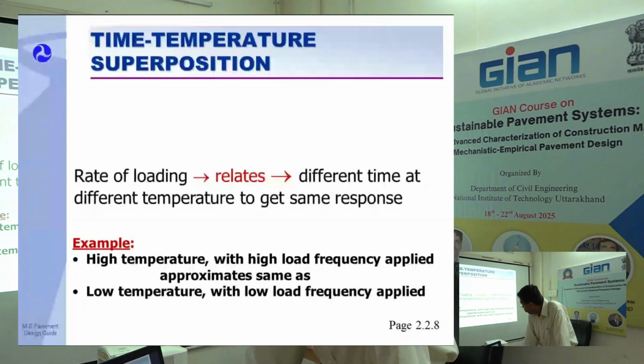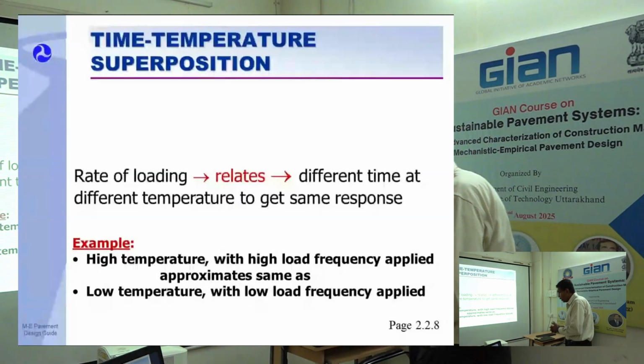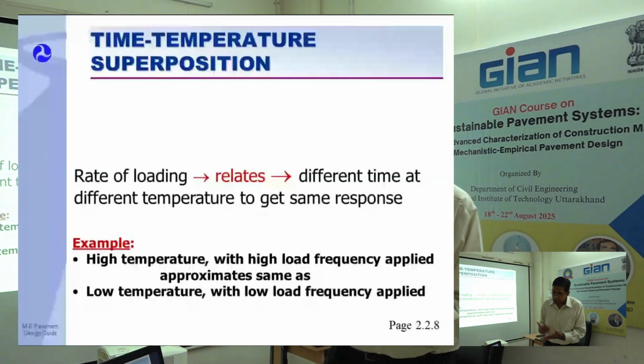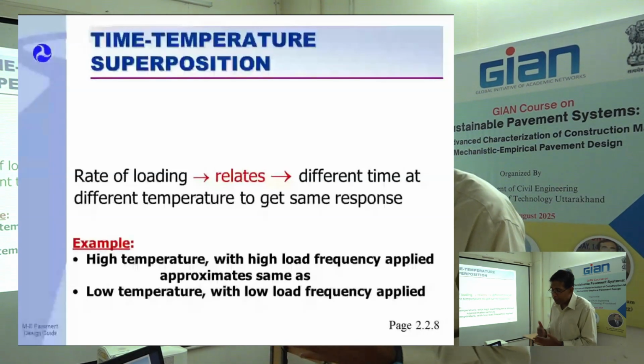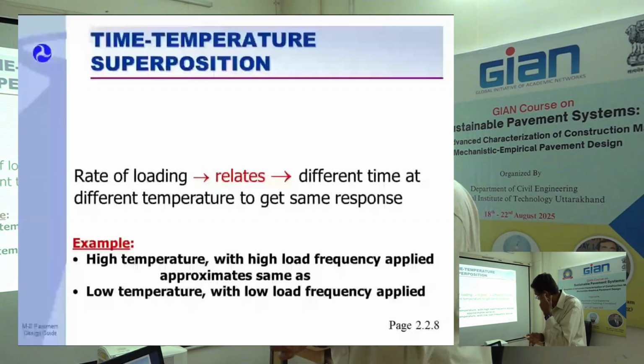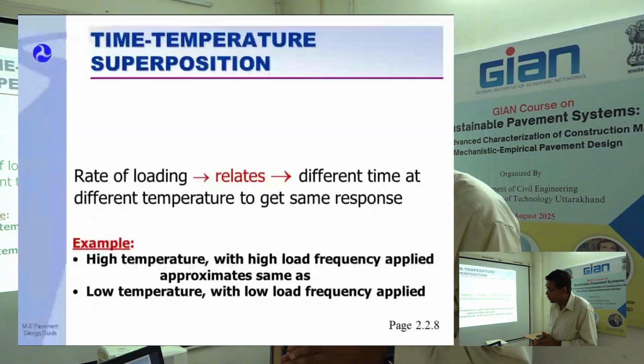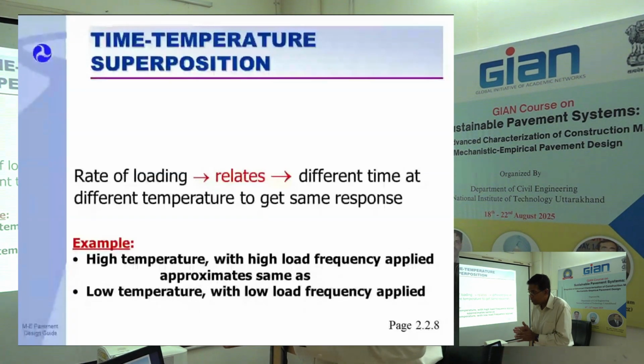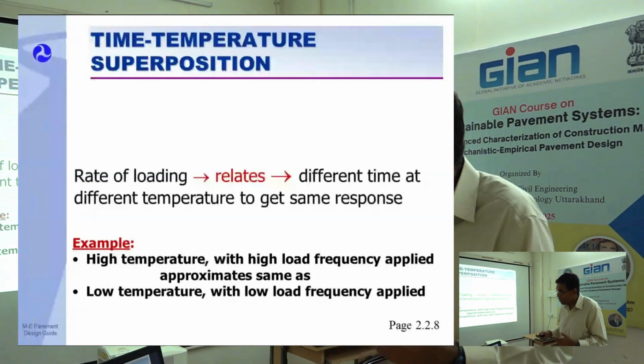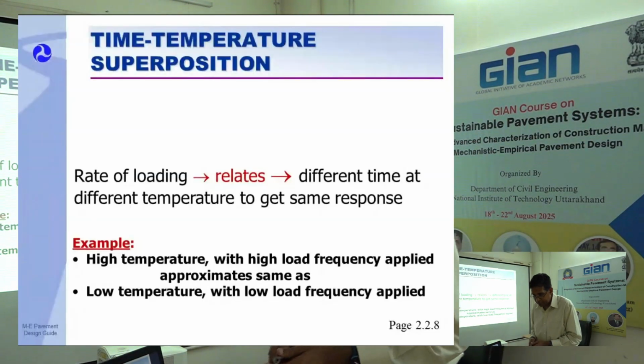Yeah, I think this is the resilient modulus. The dynamic modulus at a given temperature and frequency for asphalt is the resilient modulus. So it is the equivalent resilient modulus for asphalt concrete. So the resilient modulus in AASHTO 93 was very different. So you now have to transition from AASHTO 93 to pavement ME or MEPDG. So that resilient modulus that I kept talking about up to this point for asphalt is now the dynamic modulus. So you're not missing anything. The only difference is that the dynamic modulus at a particular frequency and temperature is the resilient modulus, or the E value, that will become the input parameter. I hope that answers your question.